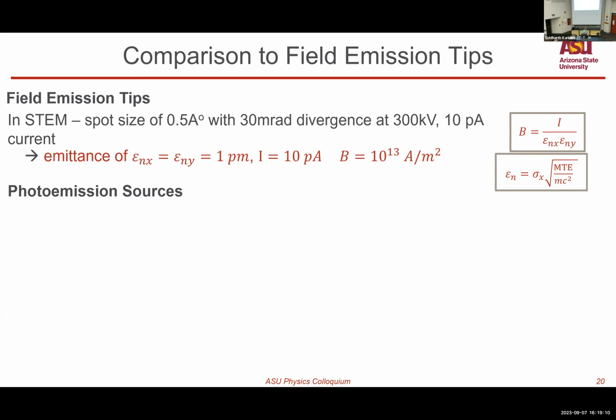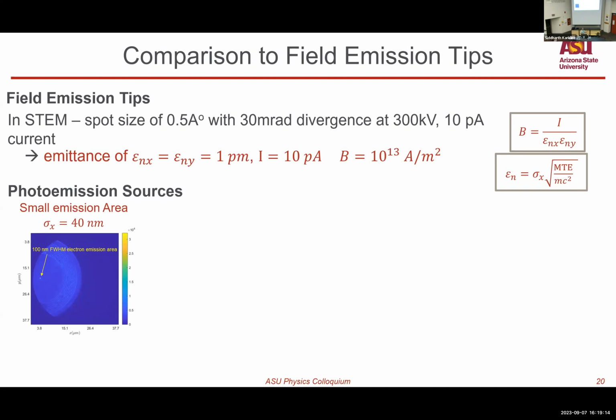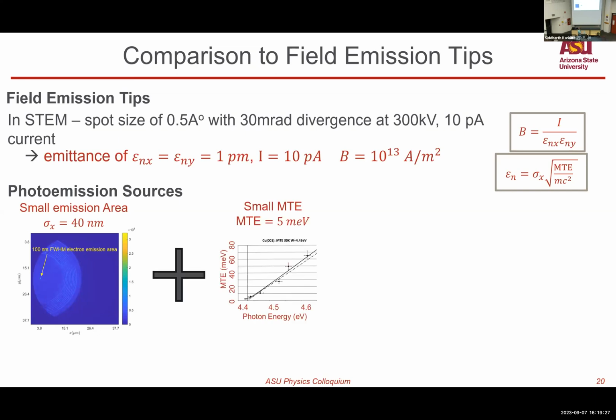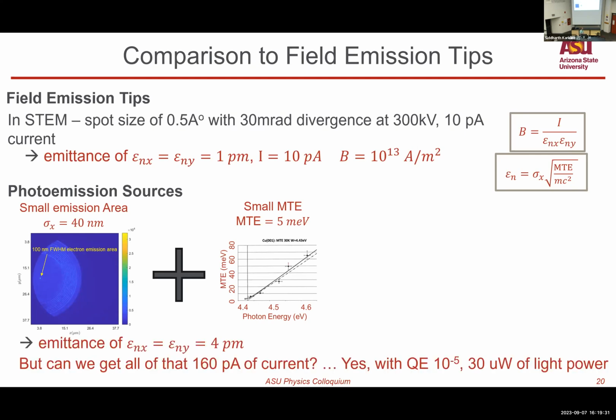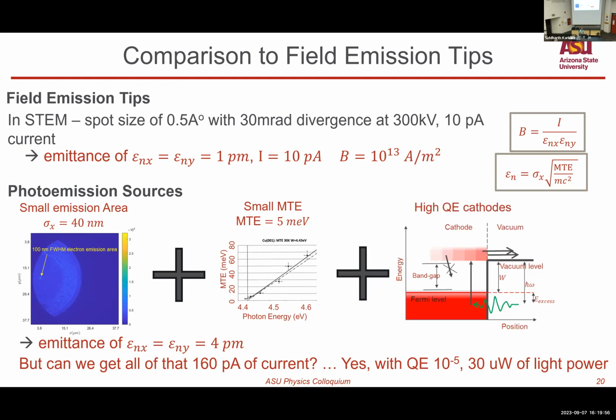Now consider photoemission sources. We demonstrated the smallest possible emission area, which had 100 nanometer full width half max, which converts to sigma x RMS spread of 40 nanometers. If we are able to combine it with the small mean transverse energy that we have demonstrated, the 5 millielectron volts, we get an emittance of 4 picometers, which is very close to the 1 picometer emittance obtained in electron microscopes. And to get the same brightness of 10 to the 13, we would need a current of only 160 picoamps. Is this possible? Yes, with a 10 to the minus 5 quantum efficiency with 30 microwatts of light, you would get this current. And very likely you can get this with high quantum efficiency surfaces. So if we want a photoemission source to beat the field emission tips, all we have to do is combine these three technologies that we have already demonstrated.